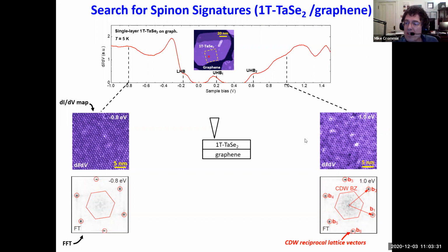And so we took the 1T TaSe2 and we put it back onto the graphene. So we got rid of the 1H TaSe2. We don't need it anymore. It served its purpose. So now we're back to the 1T TaSe2 on graphene. And here I show dI/dV images both at very low energy and very high energy. And when you look at them, you see basically the only periodicity, the main periodicity that you see, is the Star of David CDW periodicity.